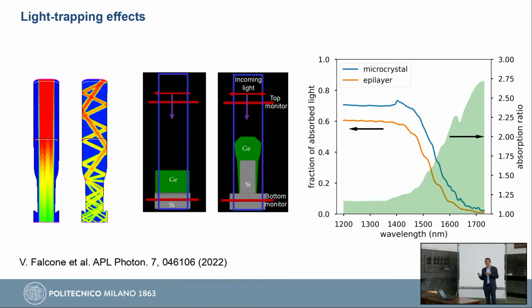So we did this properly, solving Maxwell's equations with a finite difference time domain approach, and we compared two systems. One is a flat germanium layer, let's say 5 micrometers thick, and the other is this faceted microcrystal, which is also 5 micrometers thick. So the amount of absorbing material is the same. It's only the morphology which is changing.